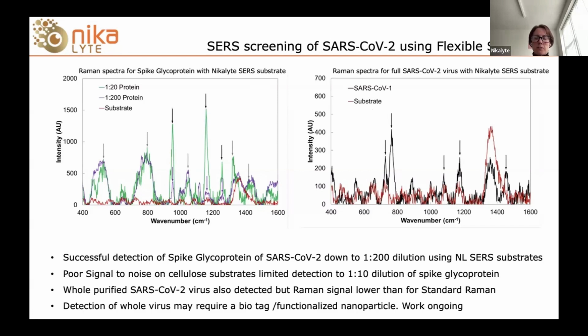And that could involve potentially using a tag, or a functionalized nanoparticle. In this work, the gold nanoparticles were bare, so there was no receptor or binder to bind the molecule to the nanoparticle. And the work is ongoing now, and Dr. Gia's got some new substrates from us and is looking at ways to functionalize the nanoparticles to improve the detection of the virus. But this is very encouraging results. The first time we've done any work with detection of viruses and proteins. So we're very excited to see this step in the process.